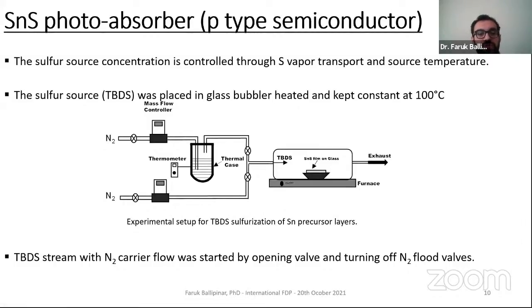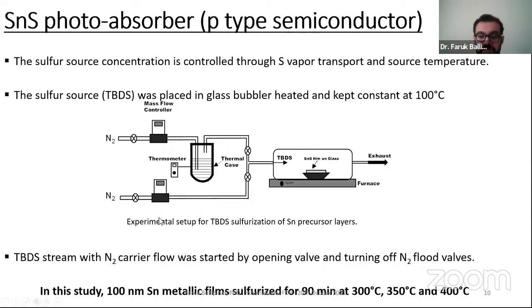TBDS sulfurization for tin sulfide material was the first application of its kind in the literature. We developed it. TBDS has some advantages over the other sulfur sources, H2S, elemental sulfur, and other candidates in the literature. TBDS is low toxic, low cost, and doesn't require extra handling during the sulfurization process. So it was a wonderful experience for me to develop the tin sulfide film through the TBDS source for the first time in the literature.